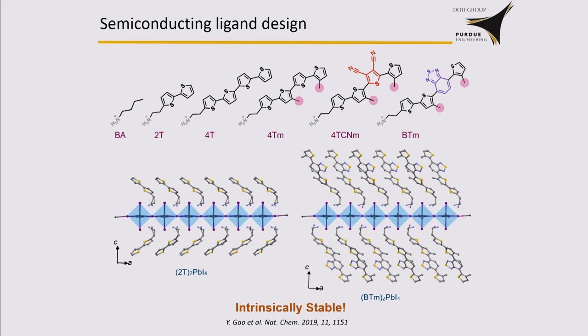And now we are able to control the property not only by tuning the inorganic part, we are also able to change the molecular design to change the optical and electronic properties for these hybrid materials. And also because of the protection effect of these organic ligands, the perovskite materials are very, very stable. They are waterproof. They do not decompose in water, and they do not decompose under high temperature, even like 200 degrees C. So intrinsically stable.